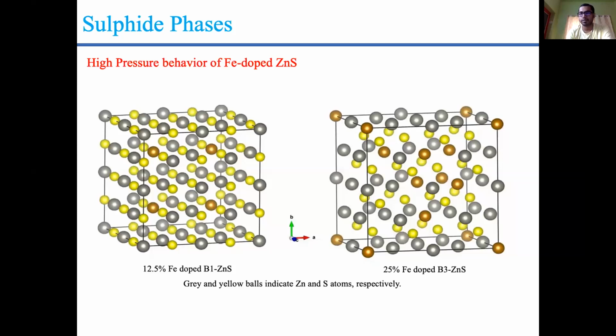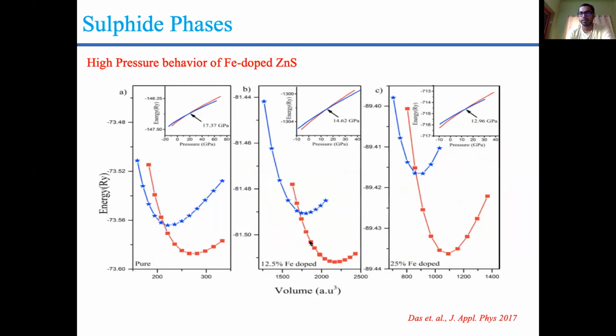The first thing is to draw the equation of state of these structures. Here you can see the equations of state for the pure, 12.5%, and 25% structures. This is purely the energy-volume curve, and from there we can calculate the enthalpy. Here the enthalpy versus pressure is plotted for the two phases, and their crossover denotes the transition pressure from the B3 to the B1 phase. In the pure phase, I got a transition pressure of around 17 GPa, whereas increasing Fe content decreases the transition pressure to around 13 GPa. So you can see this is the phase.